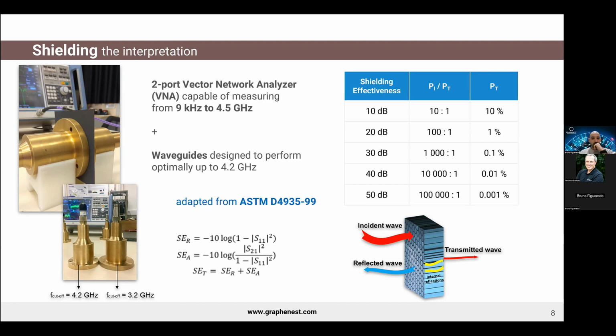So on the left side of the slide, you see the equipment that we use at Graphenest to measure the shielding effectiveness. And it's basically composed by a two-port network analyzer, a VNA, which is capable of performing measurements optimally up to 4.2 gigahertz. Of course, this depends on the waveguides. As you can see, we have at Graphenest two waveguides, one with a cutoff frequency of 3.2, and another one which was built with a cutoff frequency of 4.2 gigahertz.